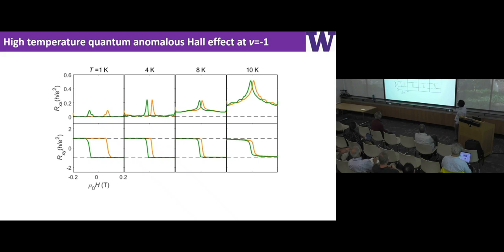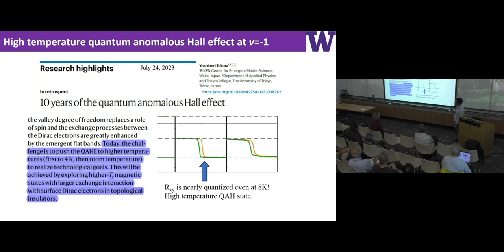One feature I want to show you first is the temperature dependence. I emphasize that even at 8 Kelvin, Rxy is still nearly quantized. You may not appreciate this number, so let me show you this paper from Yoshi Tokura. We know that the QAH effect was initially discovered in 2013, so this year marks the 10-year anniversary. This is a review article published about a month ago about the quantum anomalous Hall effect. What you see at the end is that the challenge today is to push the QAH effect to higher temperatures, first to 4K, then to room temperature.